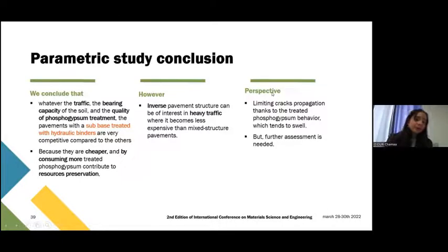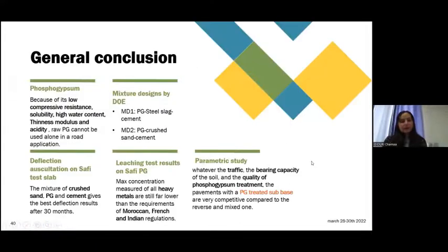As a perspective, limiting cracks propagation thanks to the treated phosphogypsum behavior, which tends to swell. But further assessment is needed. And we conclude in general that phosphogypsum, because of its low compressive resistance, solubility, high water content, thinness modulus and acidity, raw phosphogypsum cannot be used alone in road application.